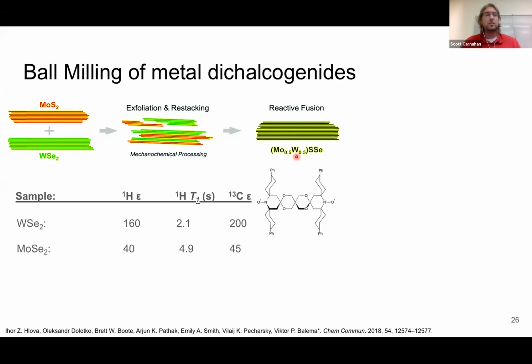I was doing traditional TEKPol TCE solution DNP on these, and we were getting good enhancements of the solvent, and I was getting selenium DNP spectra. Then the moment we went to the ball milled sample, we got no enhancement, and we saw that the proton T1 skyrocketed. After the annealing step, we were able to get solvent enhancements again, and the proton T1 became much more reasonable. The red flag for us was the proton T1 shooting up, which means that the TEKPol in our solution was probably getting eaten up in some way.